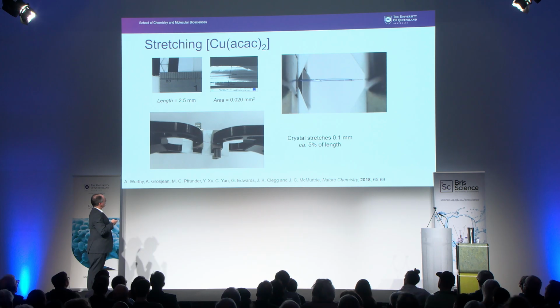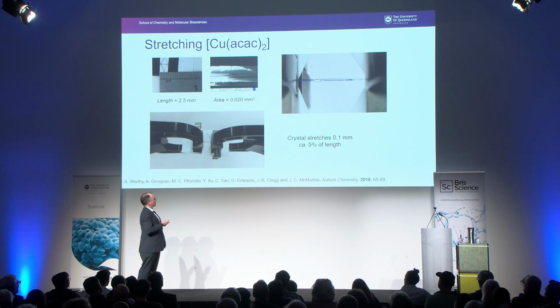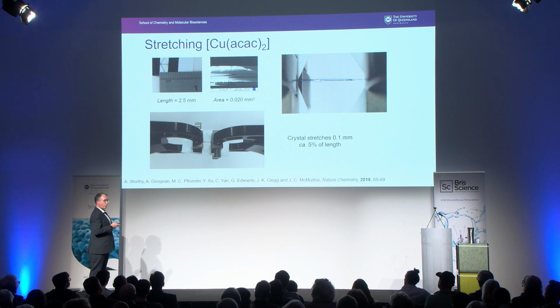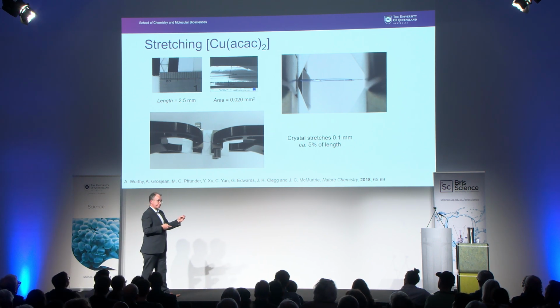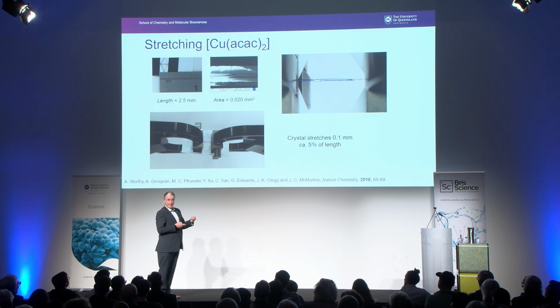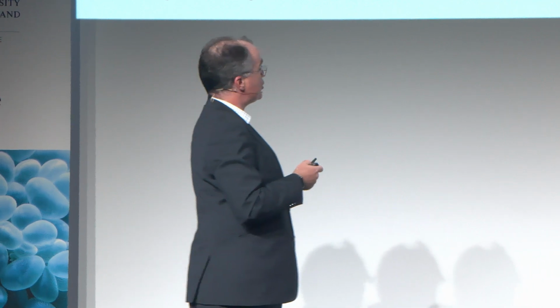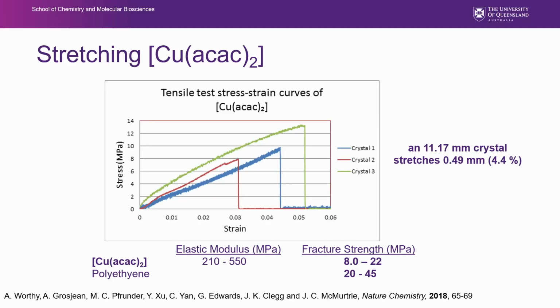And when you do that, you apply force equally and you monitor how far this crystal extends. And it turns out you can stretch a crystal of about 2.5 millimeters by about 0.1 millimeters, which is nearly 5% of its length. So that's quite a way. But also when you're doing this, you can measure how much force you're applying, and that will also tell you about the elasticity that you're experiencing. So you recall when I said something that is elastic has a linear relationship to how far you can stretch it. So when you measure these things, you can get linear plots out, which demonstrates elasticity is present.